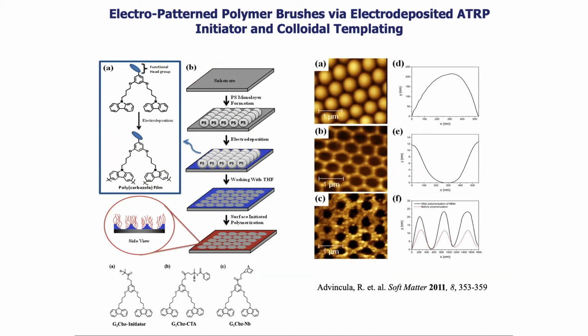In other cases, we demonstrated that the patterning can be done where the electropolymerization actually occurs on the pattern, not on the holes. So in this case, we electrodeposited an ATRP, a RAFT, and a metathesis initiator. After grafting the initiators on the surface, you get this pattern in the middle. And then after growing the polymer brush, you can see the brush formation on top of the pattern.